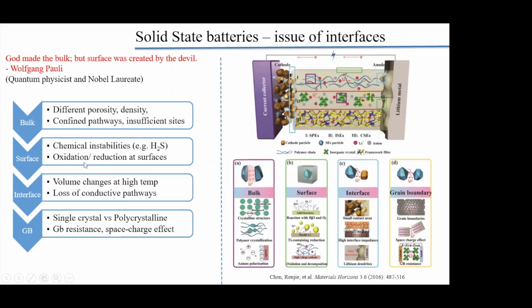And then at the interface, many of these small interfaces between the particles, between the electrolyte and the electrode, you need to make sure there are no drastic volume changes at high temperature. As the cell starts working at high temperature, it should not lose conductive pathways. If, because of high temperature, one of them expands rapidly and loses contact with the other interface, then you lose this pathway, and lithium cannot go to the other side because of excessive volume change.